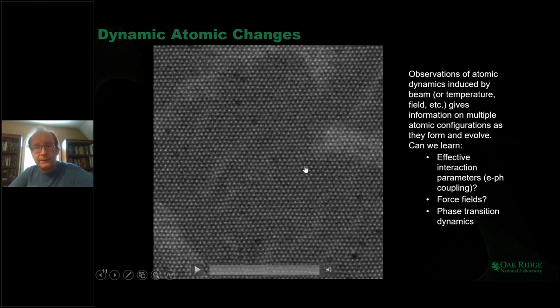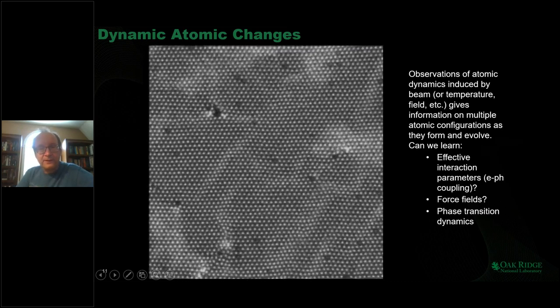What you see on the slide is the image of a monolayer of a layered transition metal chalcogenide, molybdenum sulfide, which is being visualized on the electron microscope. So the blobs here are atoms. These are either molybdenum atoms or the two sulfur atoms. You can see a number of vacancies. The missing sulfur atoms look like dark spots. So it looks great.